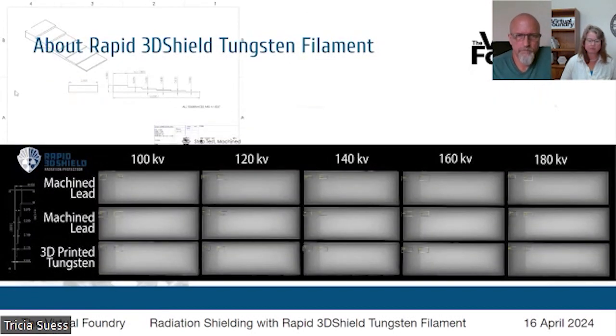Now, how about those results? What you're seeing here is an X-ray test up to 180 kilovolts. The top and middle rows are machined lead in the step test shape you see in the upper left corner of the screen. The bottom row is that same shape 3D printed in our Rapid 3D Shield Tungsten Filament.